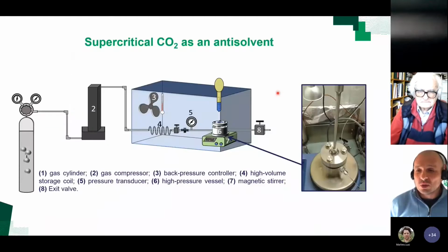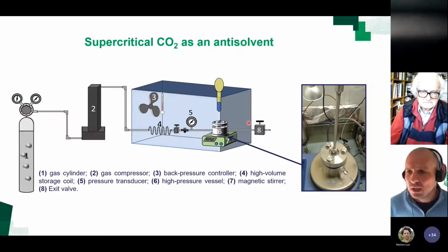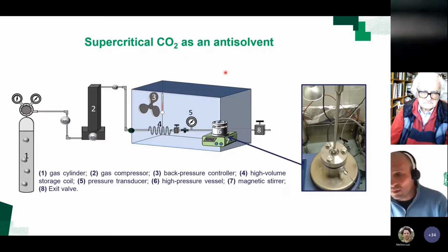Now, using CO2 as an anti-solvent, one of the methods that we have used in our lab facilities here in Bernal is using CO2 as an anti-solvent in a very simple way, which is again taking a bottle of CO2 and compressing the CO2 further using a high pressure pump, pressurizing at the right pressure and the right temperature inside an incubating chamber, and then the CO2 will be inserted into a high pressure vessel, right?